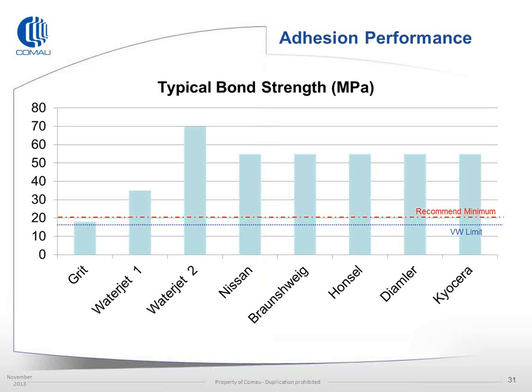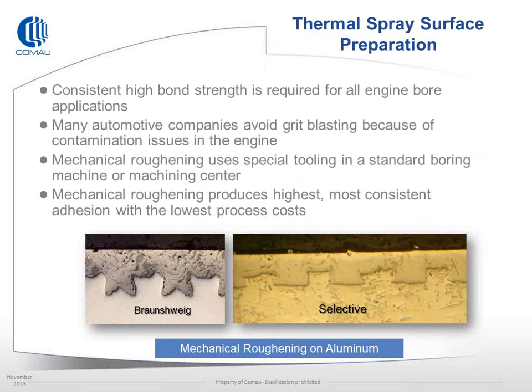These aren't guaranteed results. It's just giving you an idea what the difference is between a grit blast, water jet, and the various mechanical roughening processes. To give you an idea what the Braunschweig looks like, the bottom left image gives you a cross-section and shows you how the dovetails are cut into the surface prep with the coating sitting on top and the aluminum below. The selective prep process being evaluated can produce a grooved area, and then through mechanical deformation of the positive portion of the grooving, we get a dovetail formed by the deformation and providing sufficient adhesion results.